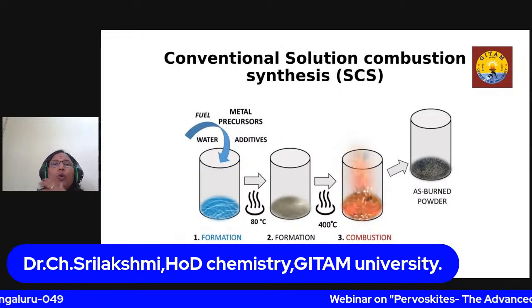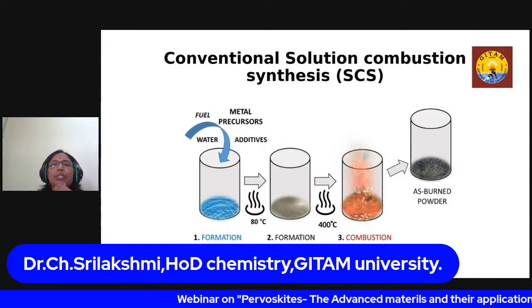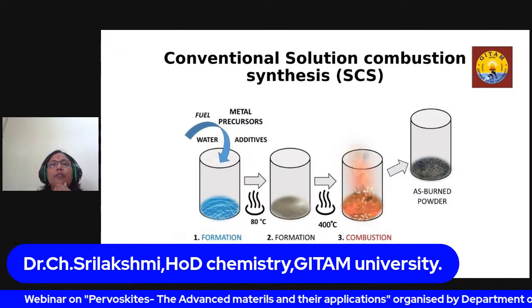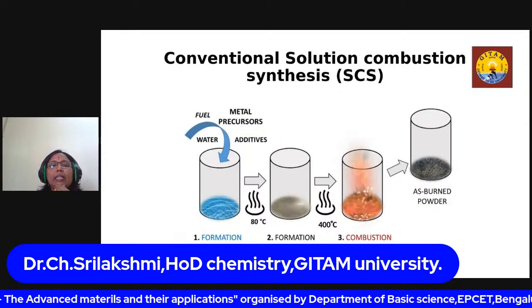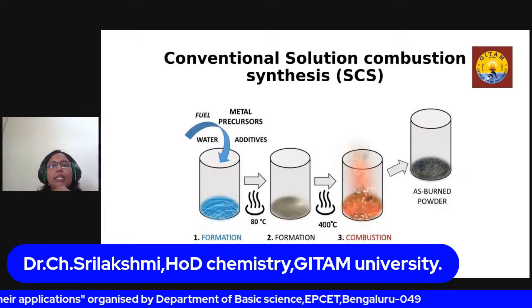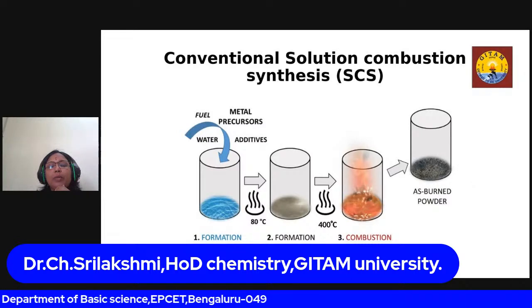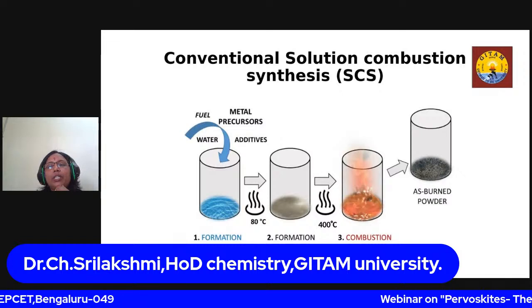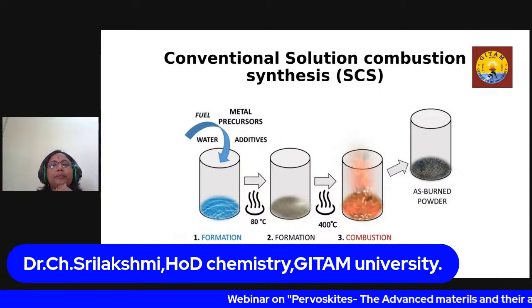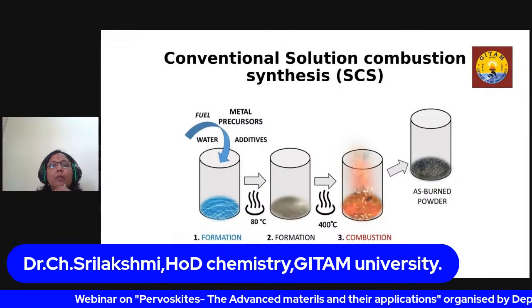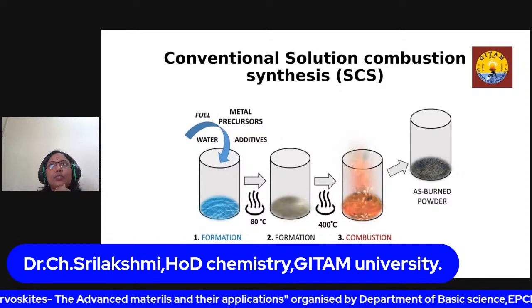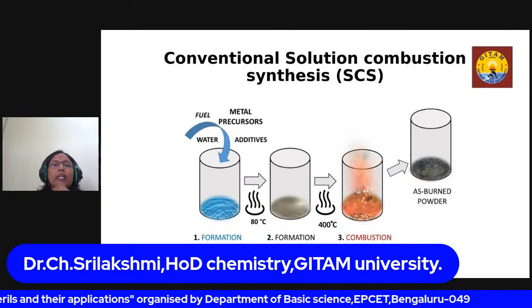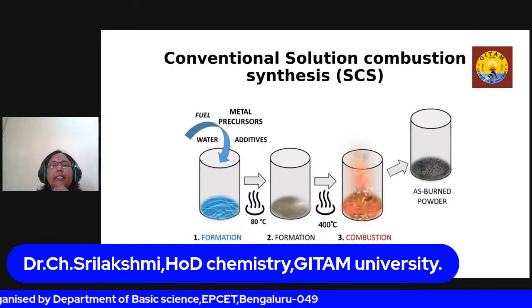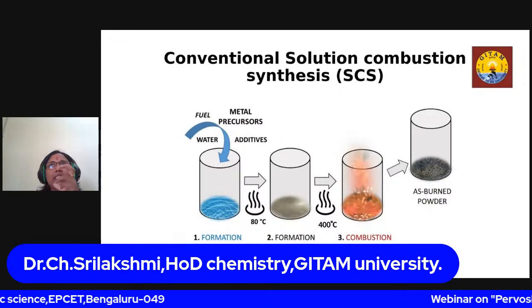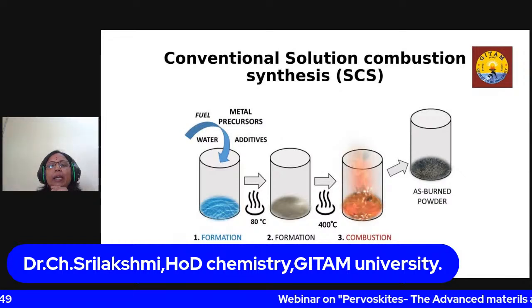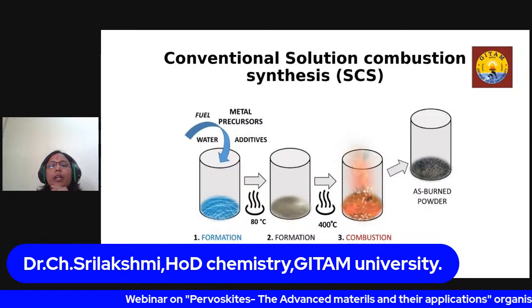Before going into the modified solution combustion synthesis which I developed, let's see the conventional solution combustion synthesis. It consists of three steps: formation of the combustion mixture, formation of gel, and combustion of the gel. Initially, to form the combustion mixture, we dissolve the metal precursors, which also act as oxidants, and the fuel in the required amount of water, and this is treated at 80 degrees C. Due to dehydration, it forms a gel-like structure, and this gel should be kept in a preheated furnace or oven at 400 degrees C.